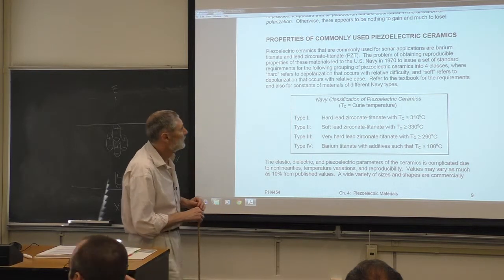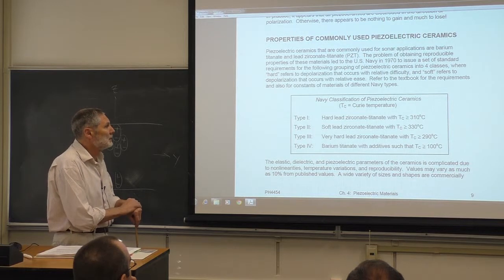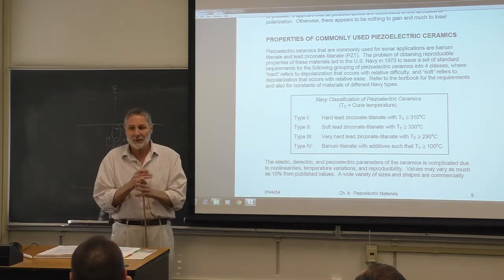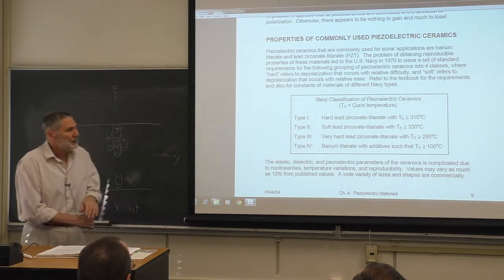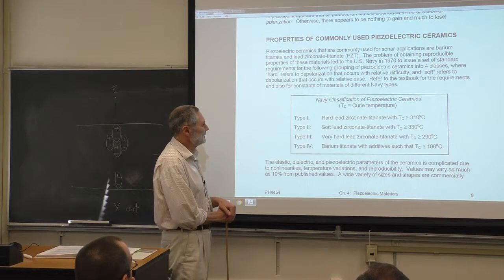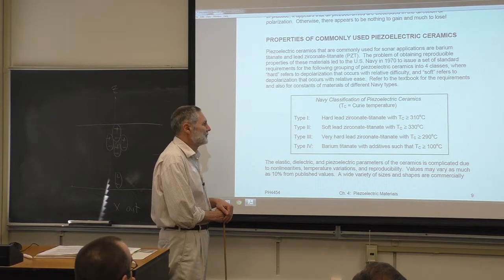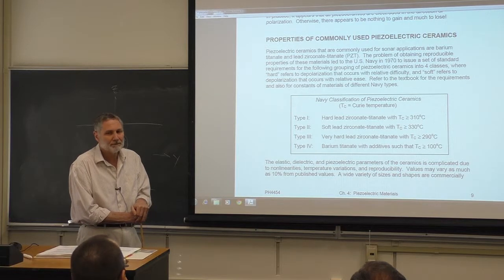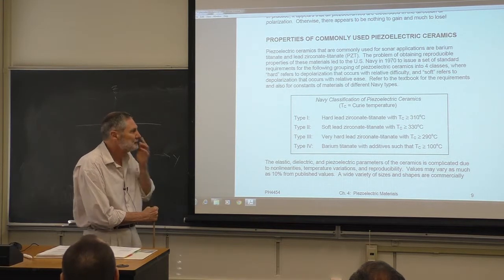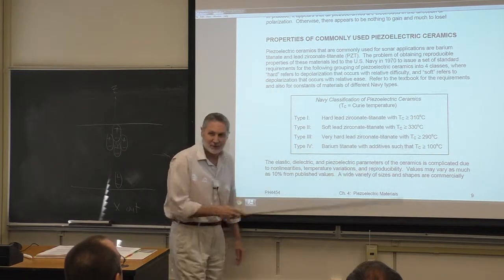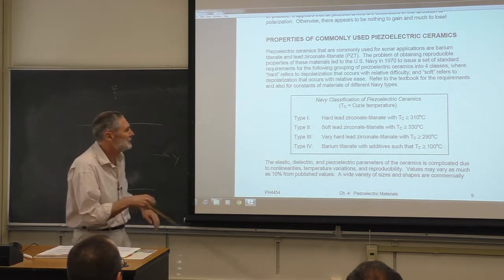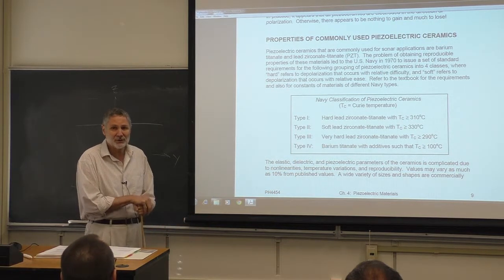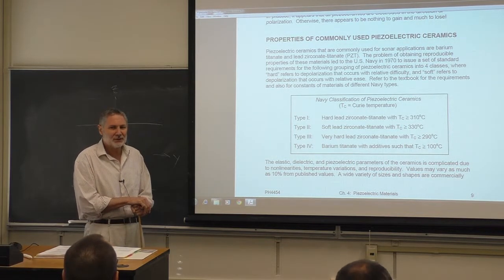A student asks why the soft material has the highest Curie temperature. The hard and soft classification refers to how hard it is to depolarize under driving conditions — like the stresses or strains needed to depolarize it — not directly to the Curie temperature. The soft materials tend to be more sensitive, which is what you want for hydrophones. You're not going to subject a hydrophone to a lot of strain, with the exception of blast wave measurements.